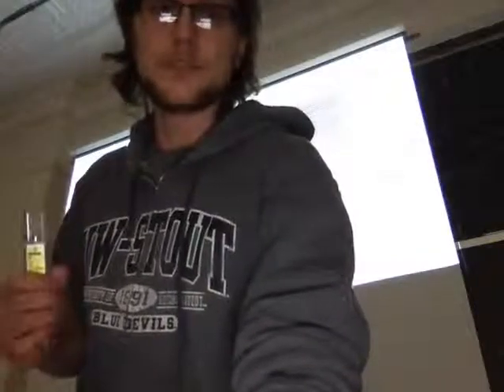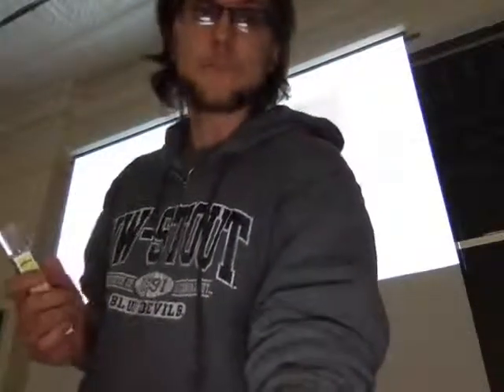So we can have electronic states introduced due to a polaron. People were researching these in the 60s, looking for solutions. One paper I came across found that for an appropriate coupling range, from about 2.5 to 6, these bound states are stable enough.